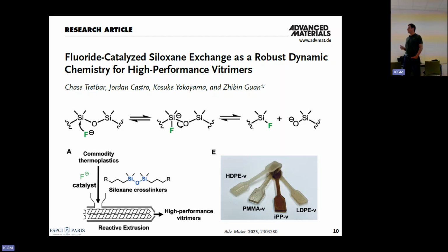So here I think it's good, I should be very careful when I speak about fluorine chemistry, so I'm not going to go into detail, but you can activate this bond with fluoride anion, and then you can have the exchange reaction between this siloxane and this SiF bond. This chemical reaction is compatible with high temperature. It does not require a catalyst, just a source of fluorine, and so typically it's used with KF and polyether.